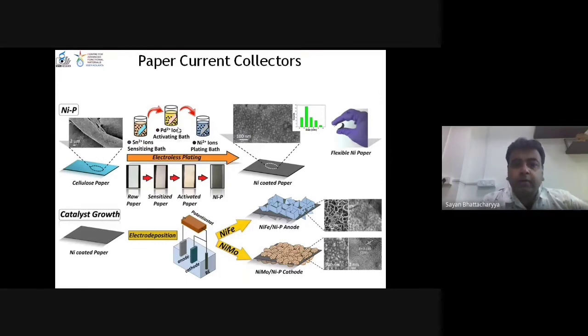And finally, from this palladium coated paper, he put it on Ni2+ salt. So here, palladium reduces nickel-2 to nickel-0, that is metallic nickel, and we have the nickel nanoparticle coated paper. This is, as I'm saying, very easy. It is not easy, and we took a long time to get this, frankly speaking, and you can basically bend it. I'll show you soon.